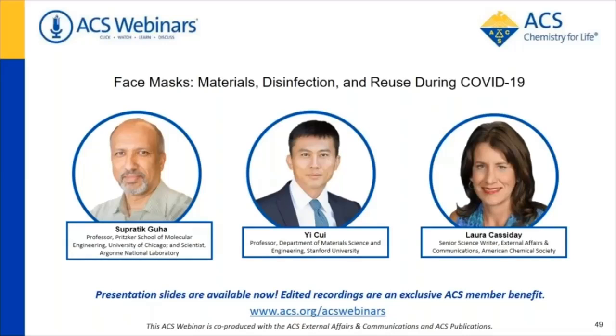Okay, very good. Yi, the next question is for you. Would the disinfection methods you examined work for surgical masks as well as for N95 masks? Well, for surgical masks, I found in a recent study that in some of them the meltblown polypropylene layer has static charge, and some of them actually don't. Because it's the same polypropylene material, the disinfection method we have will apply to the surgical mask as well. For a surgical mask without static charge, if you don't damage its physical structure, the treatment wouldn't affect it.